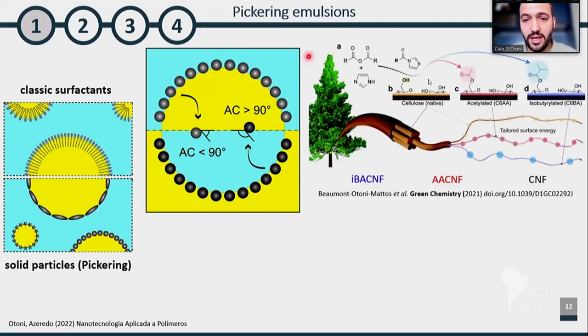So what we do with cellulose: we deconstruct biomass, and the fibrils, not the crystals, are extremely hydrophilic. So they won't be able to go to the interface by themselves. It's not spontaneous. So we have a toolbox for chemically modifying the surface of the fibrils. And this is interesting because cellulose has a lot of hydroxyl groups that are easy to attach whatever we want to. So we do some acetylation, some isobutyration, to increase the hydrophobicity of the cellulose nanofibrils, and they will go spontaneously to the interface.